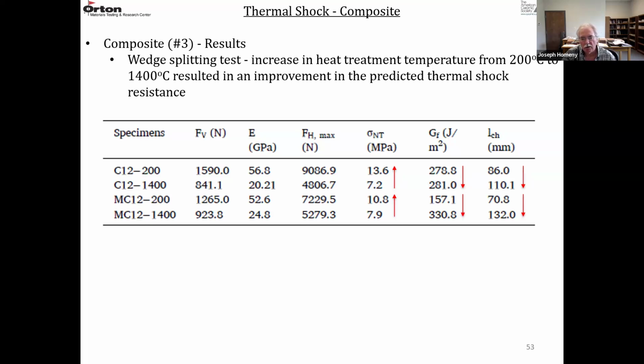So they're stronger before they're coked, but then the fracture surface energy increases after coking. This one is a slight increase, but this one, the finer aggregate material, almost doubles. So the fracture energy really goes up at the higher curing temperature for the finer aggregate size material.